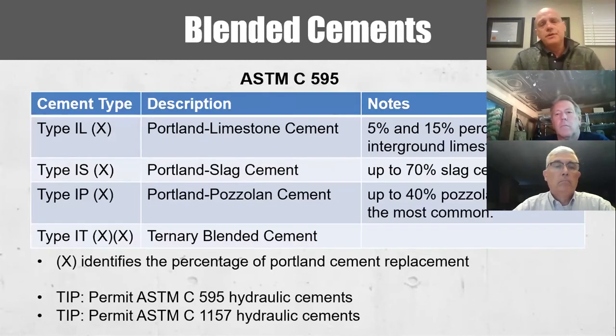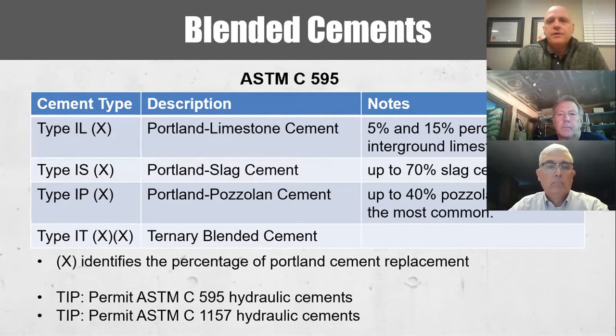Now this one is really important. Blended cements are a combination of Portland cement in addition to some other materials. The most common one is called Portland limestone cement, or type IL, and it permits in the standard ASTM C595 up to 15% interground limestone. Now, interground limestone has nearly zero carbon footprint. It usually is a byproduct of the cement manufacturing process because there's a lot of powder that is generated when crushing limestone as the raw feed for making Portland cement. So if you can take some of that powder, intergrind it with clinker at the end of the processing of making Portland cement, then you can lower the carbon footprint by as much as 10%.